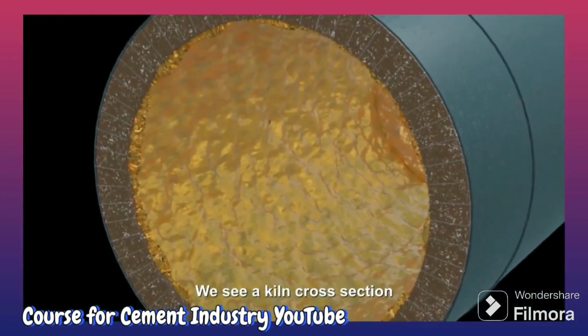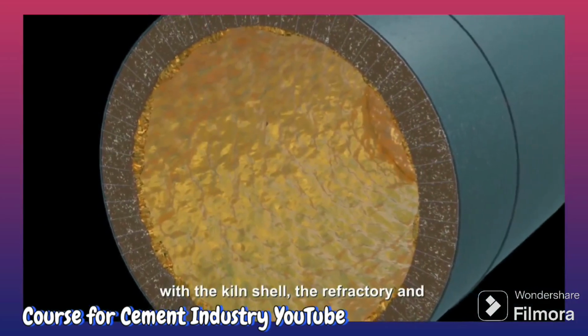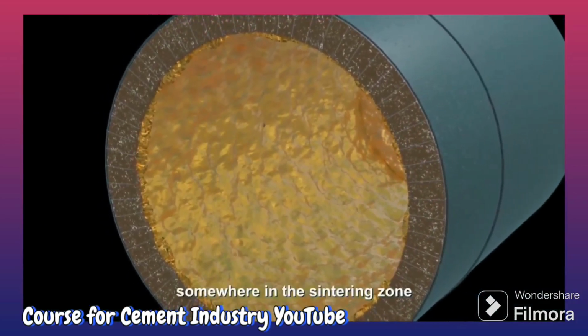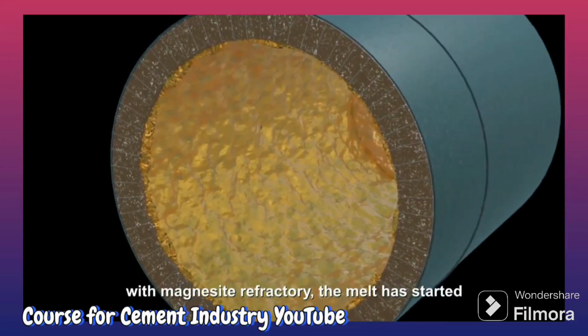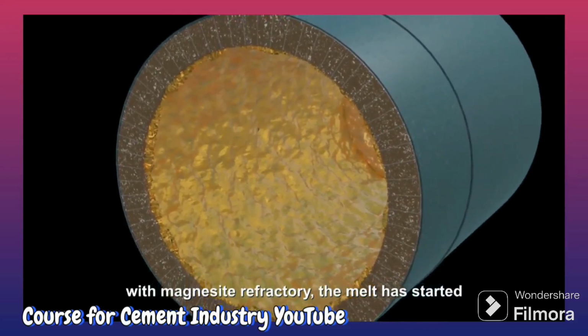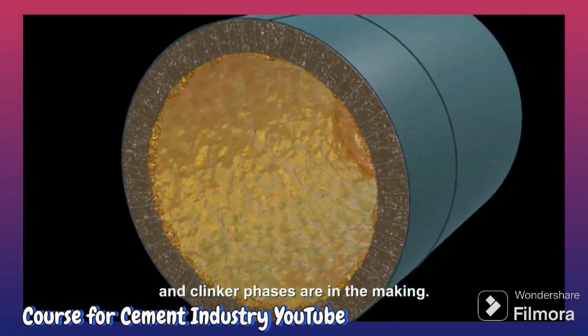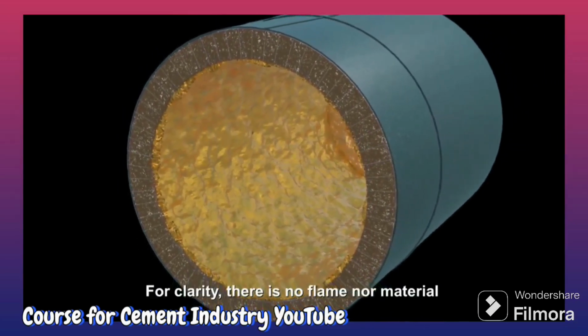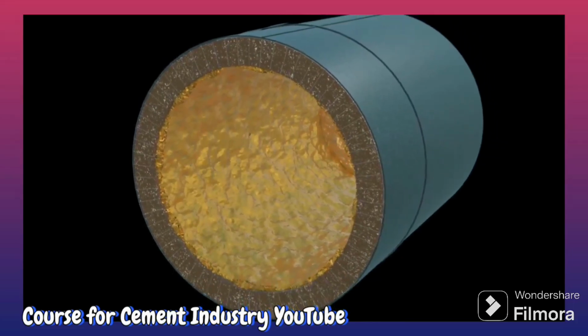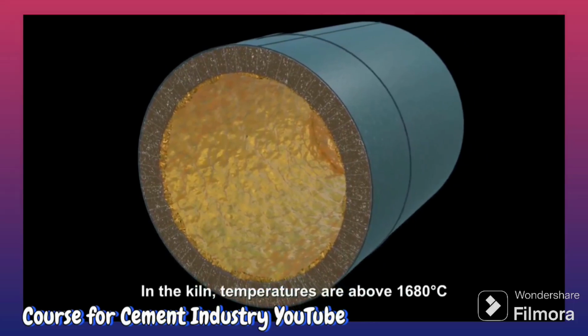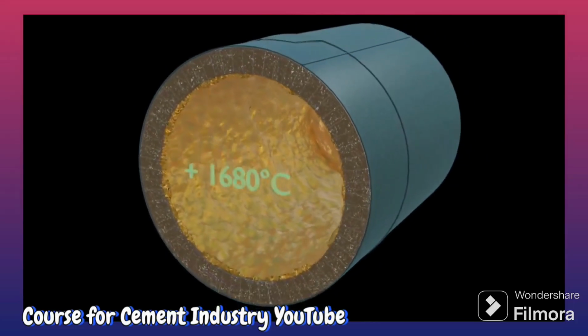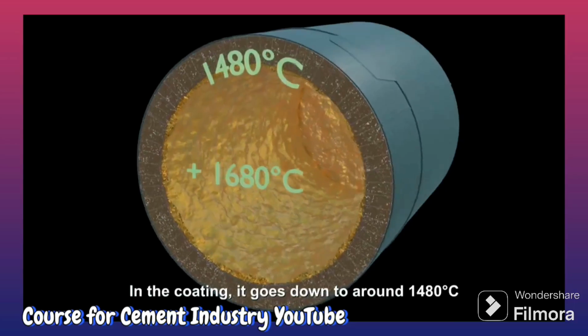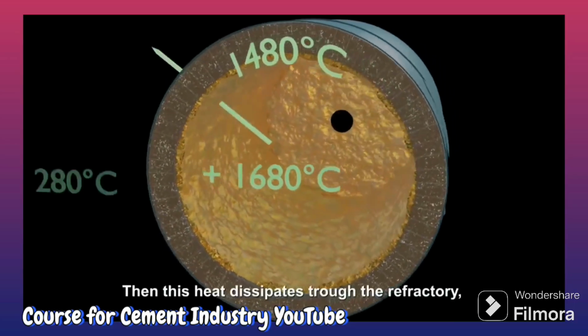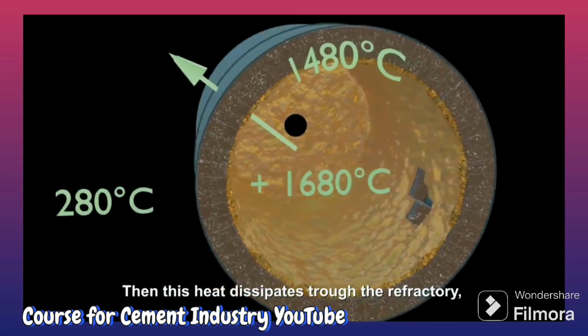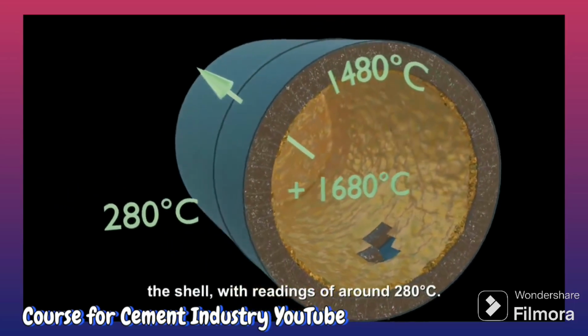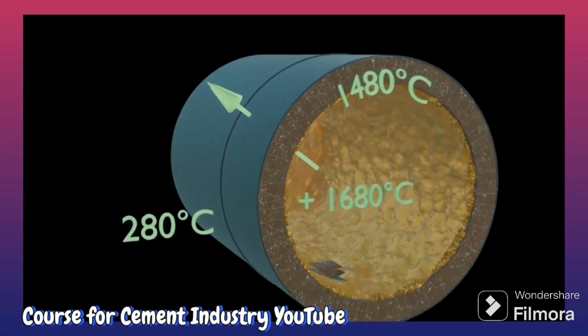We see a kiln cross-section with the kiln shell, the refractory and a bit of coating, somewhere in the sintering zone with magnesite refractory. The melt has started and clinker phases are in the making. For clarity, there is no flame nor material in this view. In the kiln, temperatures are above 1680 Celsius. In the coating, it goes down to around 1480 Celsius. Then this heat dissipates through the refractory and the shell, with readings of around 280 Celsius.